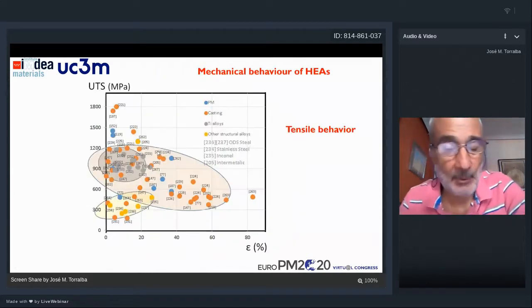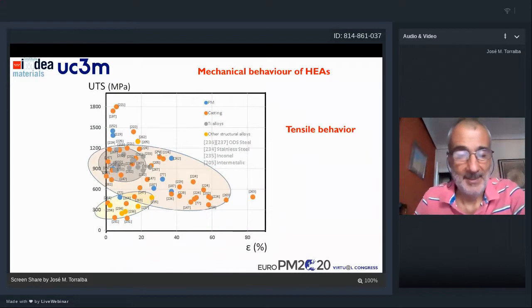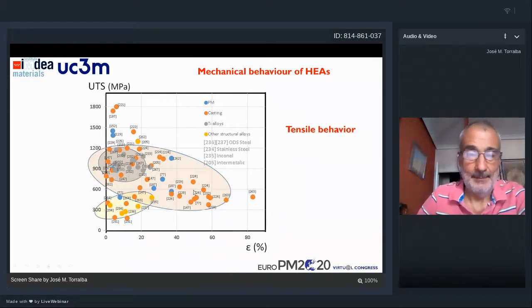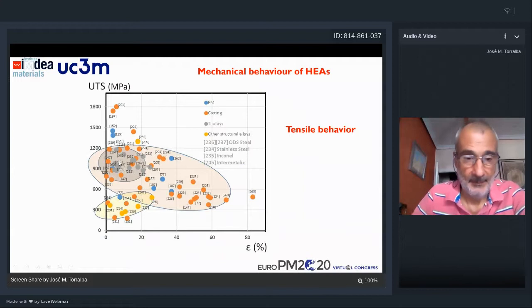We can also try to analyze the tensile behavior, but the problem is that we don't have so many papers published with tensile properties. If you see, only these blue dots are from conventional powder metallurgy, and all the others are from ingot metallurgy. And we have plotted also some other structural alloys. Here we have stainless steels, and here we have ODS steels and intermetallics or Inconel in order to compare. So we can say that even powder metallurgy materials can compete with these conventional structural alloys.